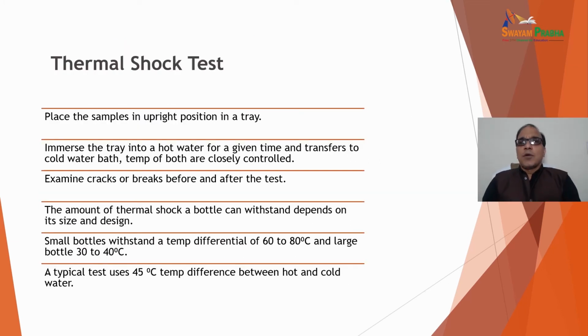Now moving to the thermal shock test. As the name suggests, can a container withstand thermal shock? Place the sample in an upright position in a tray. Immerse the tray in hot water for a given time, and transfer it to a cold water bath. The temperatures of both are closely monitored. Examine for cracks or breaks before and after the test.